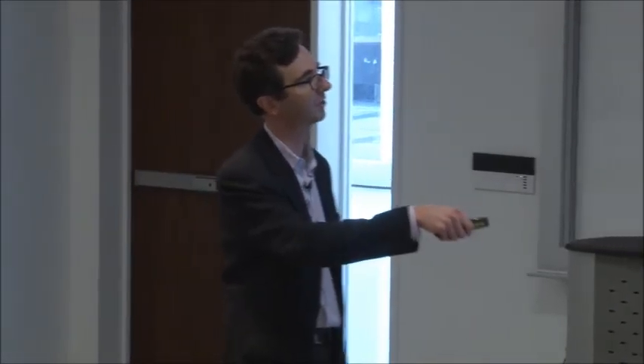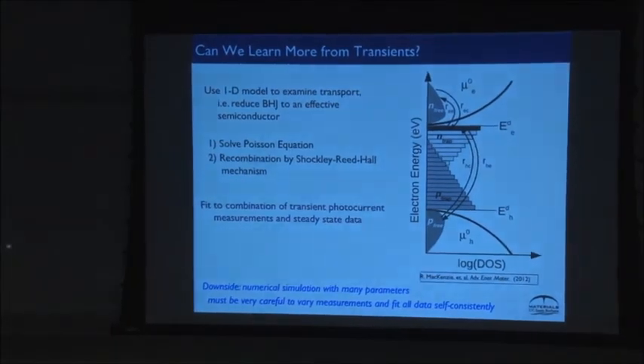And so we've kind of worked on this a bit. And what can we learn from transients? Well, I'm not going to show you all the numerics because it's a talk in itself. So in collaboration with Rod MacKenzie and Jenny Nelson at Imperial, we've done some very complicated transport simulations of data that looks like those transients that we showed before and other types of transients, where we solve the Poisson equation in a 1D model and do recombination with a Shockley-Read-Hall mechanism and actually just try to fit all the data we have, not just one curve, light dependence, time dependence, temperature dependence, and do it self-consistently.